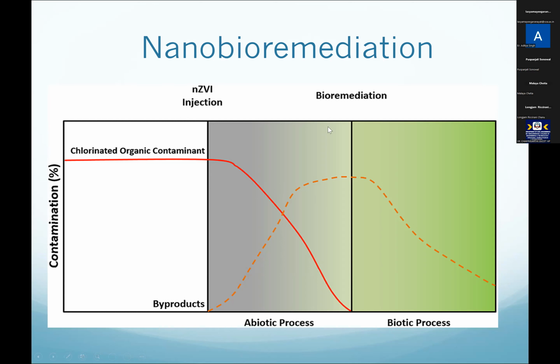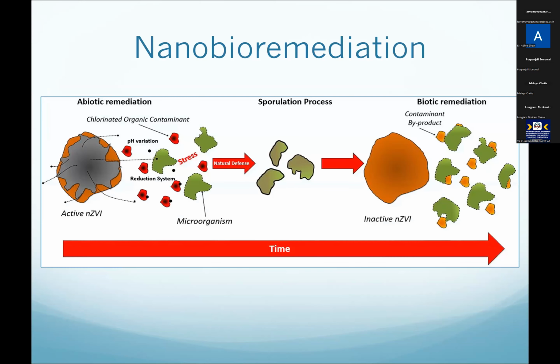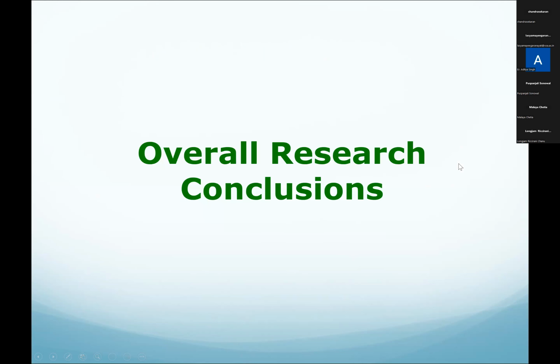So with this combination, if you don't have nano iron particles, the contamination is not going to biodegrade. So we need to add this nano to degrade this toxic contamination, or degrade the contamination to a certain level where the bio can happen. So this is the nano-bio combination. You have active nano zero valent iron particles, you have microbes, and the nano iron particles become inactive, and then the contamination byproducts that you have can be attacked by microbes. So this is the one slide.